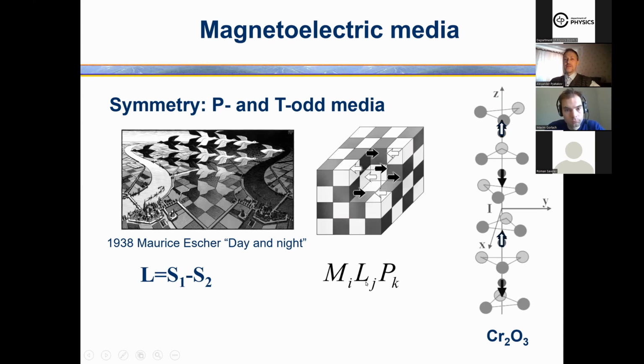So when we consider the matrix of magnetoelectric coefficients, every element of this matrix is proportional to some component of the antiferromagnetic vector, or maybe a combination of them. So the main idea of this slide is that the antiferromagnetic vector is a bridge between magnetism, magnetic vectors, axial ones, and polar vectors, electricity.